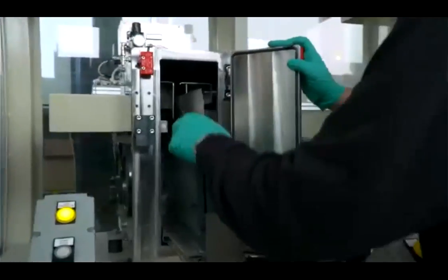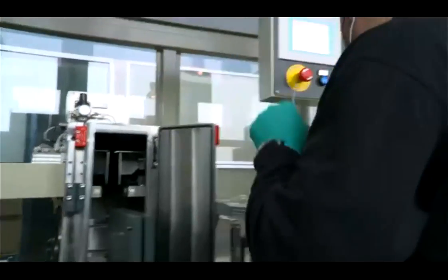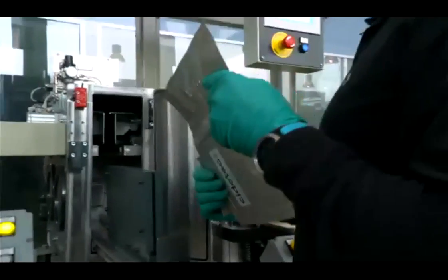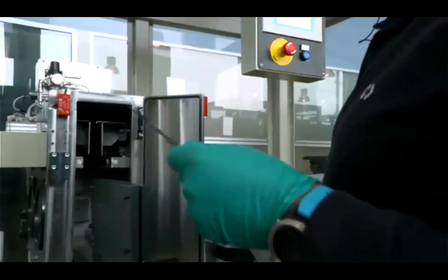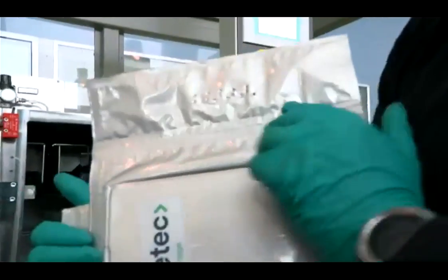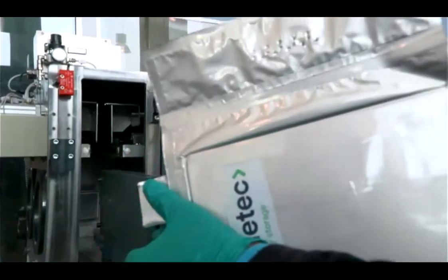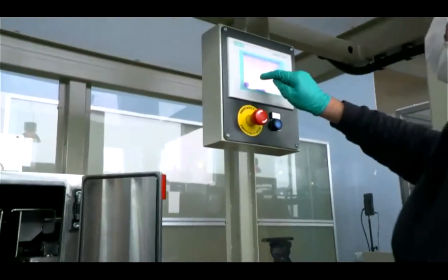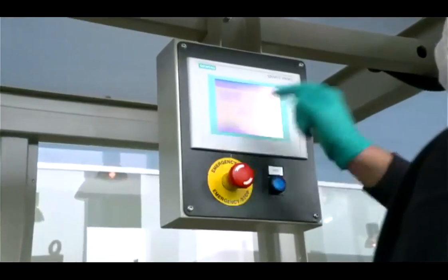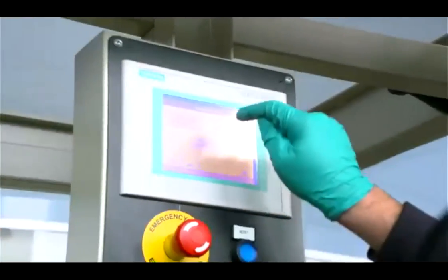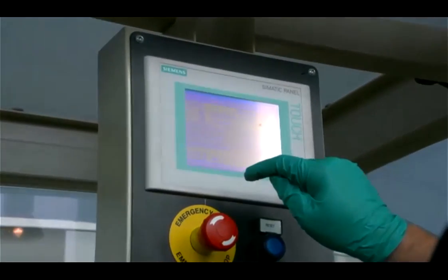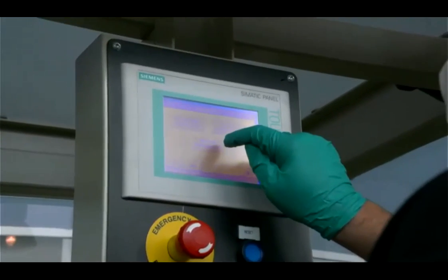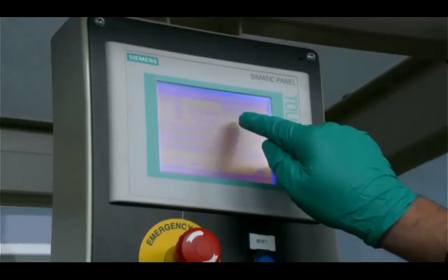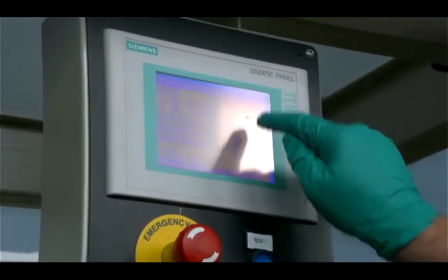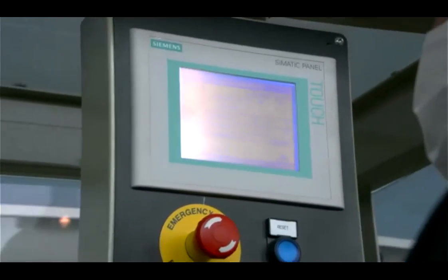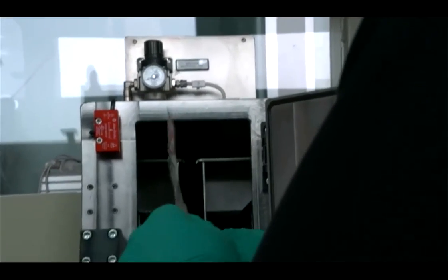What we are doing is, once we have done the forming, you can see that the cell has some place that is not marked on the stack, and this is because the cell is not under vacuum. So in this machine that Iker is showing, we insert the cell with the tabs, and with something that covers the tabs in order to avoid any short circuit of the cell. You set the vacuum in order to remove the gases, and after removing all the air, you do the sealing. So the cell is sealed under vacuum, and you can be sure that you don't have any gas coming from the air atmosphere.